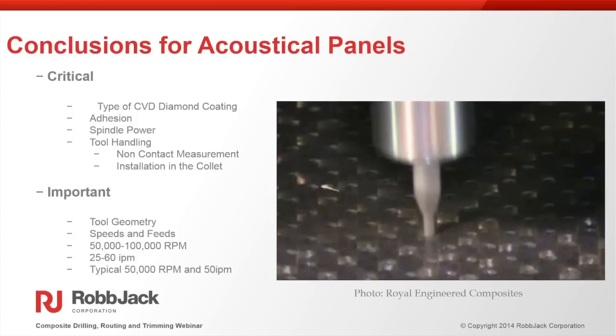So with the solution of doing these high number of holes with very small diameter tools, we found out there were a couple critical areas to get success. And the critical areas ended up being we had to design the diamond coating to have very good adhesion to the carbide geometry. Because if you have awesome geometry, but your diamond coating doesn't stick to the carbide, essentially you have a very expensive carbide tool. And it's actually even worse than just having a straight carbide tool. So that adhesion was very important to figure out.